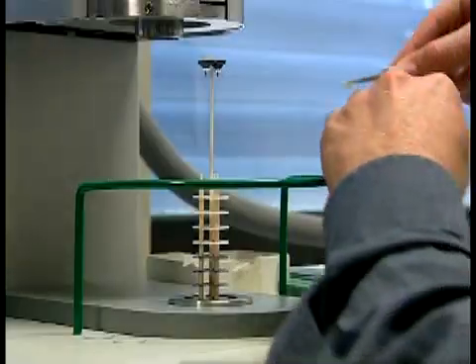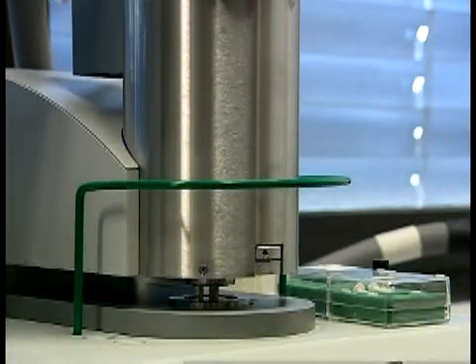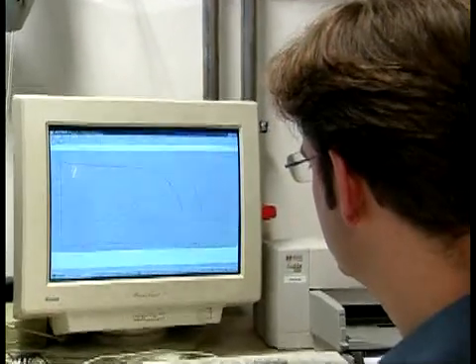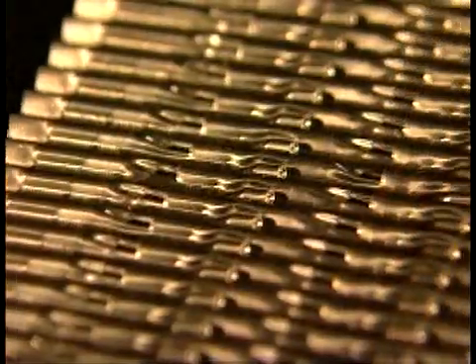A sample of diesel soot is heated in an oxygen flow inside an oven and continuously weighed with a highly sensitive scale. This diesel soot actually does turn out to be highly reactive — it begins to burn at comparatively low temperatures. Adding NO2, which can be produced in any diesel engine's exhaust, further lowers the combustion temperature. This enables the building of a soot trap. A so-called open particle filter was developed based on the Max Planck Institute's research: the PMCAT. Casing and interior are made of non-corroding stainless steel.